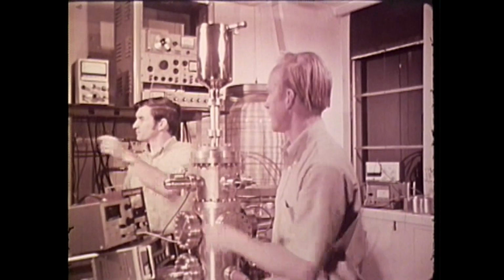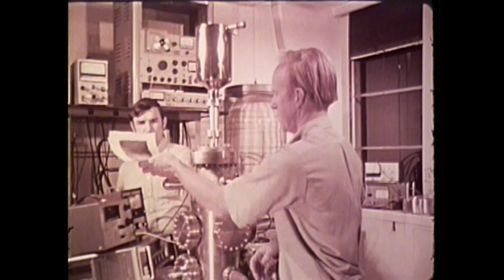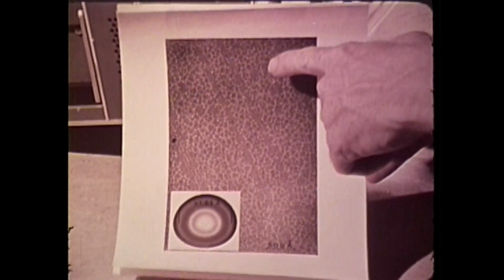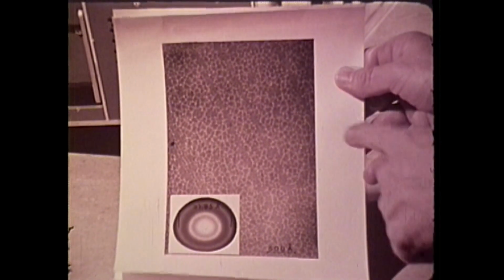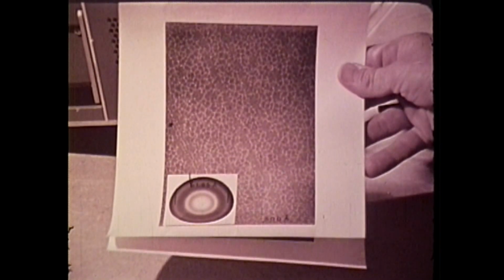Let me have those pictures. Take a look at these. See these physical voids in the film? It turns out that their presence or their absence may account for a large part of the disagreement. These voids had been predicted by indirect methods, but we were the first to prove their existence by direct microscopic observation. We can make amorphous films with voids or without the voids, so we're doing both to try to determine which properties are affected by them.